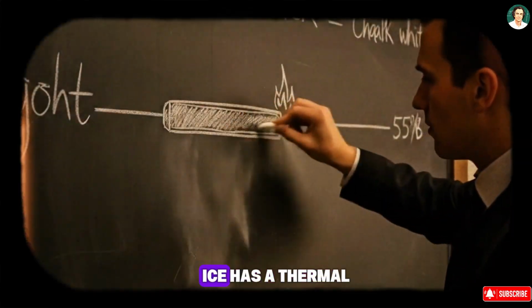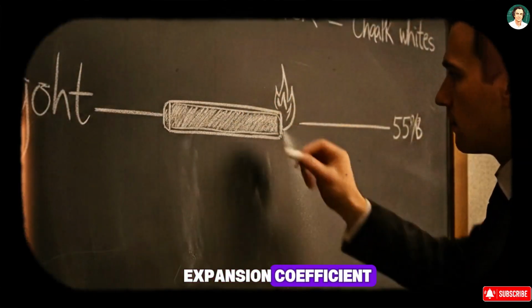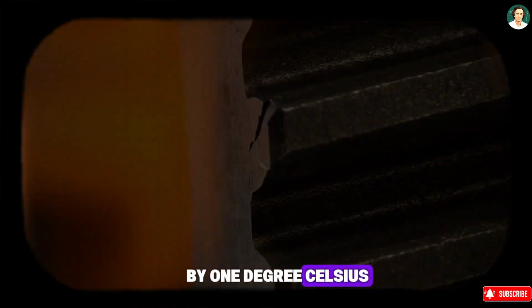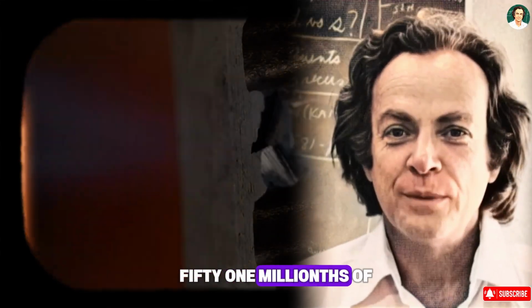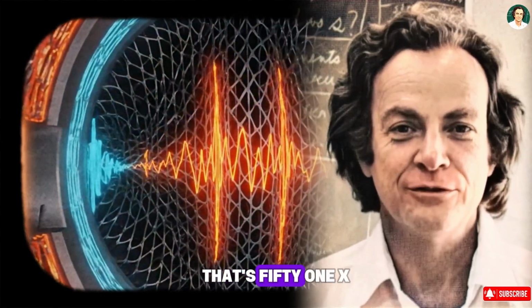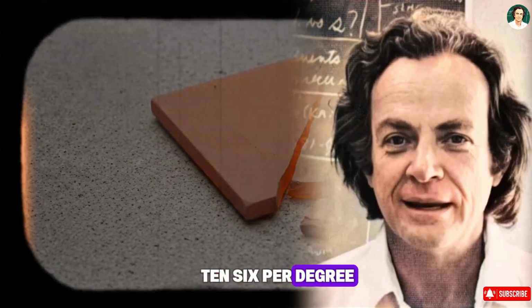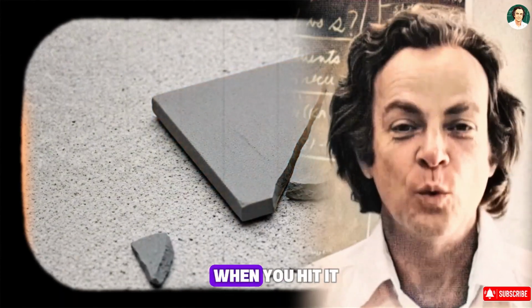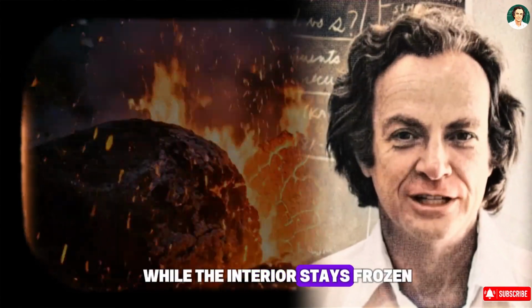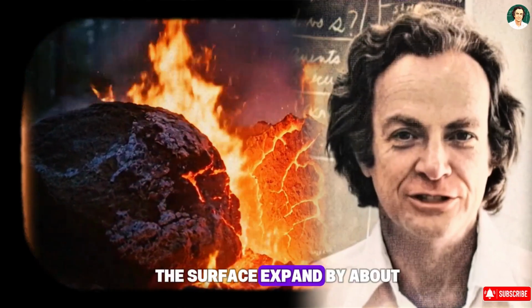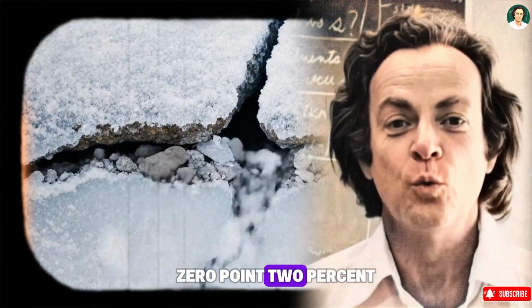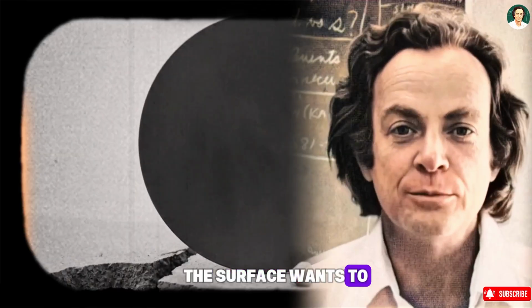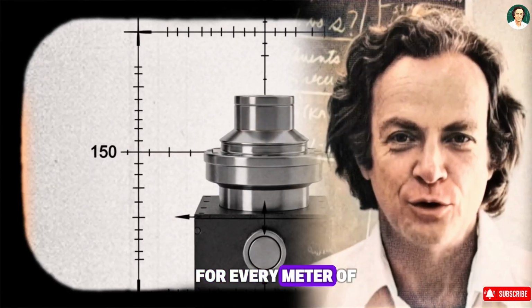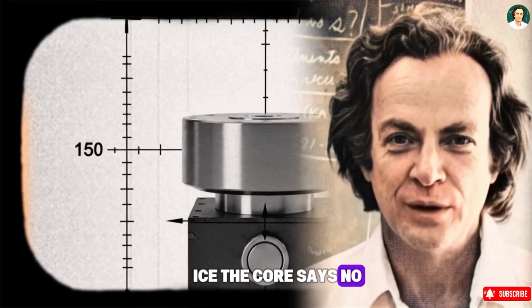Real measurements. Ice has a thermal expansion coefficient. When you heat ice by 1 degree Celsius, it expands by about 51 millionths of its original length. That's 51 x 10^-6 per degree. Sounds tiny. It's not. When you hit it with a 38 degree temperature jump on the surface while the interior stays frozen, you're trying to make the surface expand by about 0.2%, while the core expands 0%. The surface wants to be 2 millimeters longer for every meter of ice. The core says no. Think about it.